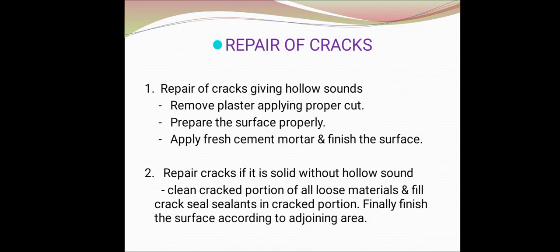Repair of cracks: First, if the crack gives a hollow sound, remove the plaster, apply a proper cut, prepare the surface properly, apply fresh cement mortar, and finish the surface. Second, if the crack is solid without a hollow sound, clean the crack properly of all loose mortar, fill the crack, apply sealants in the crack properly, and finally finish the surface around the adjacent area.